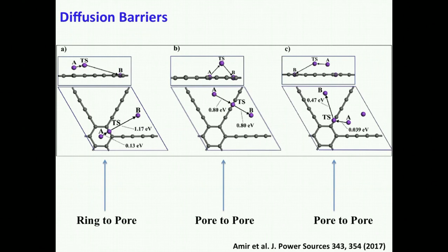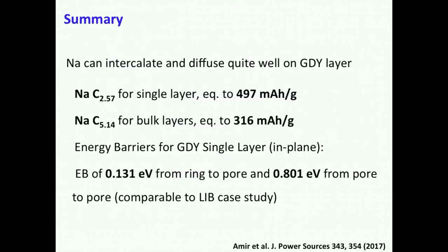So the diffusion is quite fast, the bonding is appropriate, and the storage capacity is good, which means this GDY is a good anode material for sodium ion batteries. To summarize, sodium can intercalate in GDY layers, because we have checked in single layer and bulk.